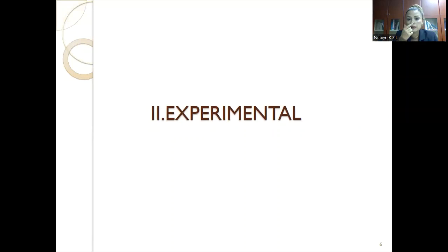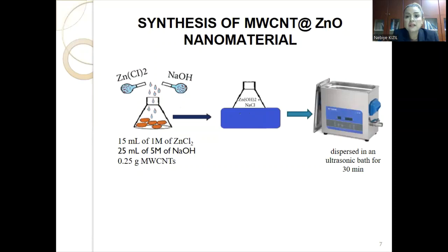This is the experimental part. Firstly, we synthesized multiwalled carbon nanotubes with zinc oxide nanomaterial. Zinc chloride, sodium hydroxide, and multiwalled carbon nanotubes were mixed in an ultrasonic bath for about 30 minutes.